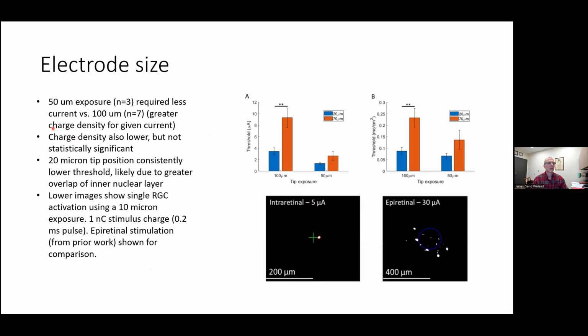So in terms of electrode size, we compared the 50 micron exposure, again, that's the length of the exposed electrode of the carbon fiber, versus 100 micron. And as you would expect, because the 50 micron electrode for a given current has a higher current density and charge density, that required less current overall. So you can see that is shown here.